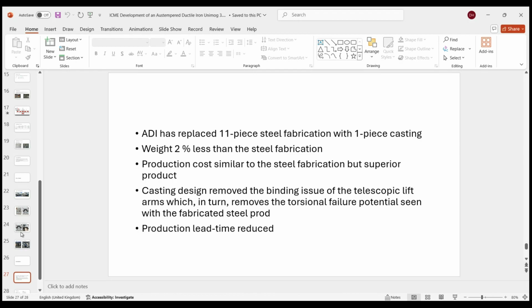This is down to the fact that, once you've got the pattern produced, and this was quite a low-cost pattern that can be produced in 4 weeks, you can then produce the castings. A typical lead time is maybe 4 to 6 weeks, sometimes a bit longer. Then the heat treatment is maybe 1 week, and the machining can be done in a couple of weeks. So you could get a part from order to door to the OEM within about 8 weeks, whereas the welded fabrication was taking longer. Don't ask me why, but I'm assuming it's basically struggling to get all the parts together, all the good welders.